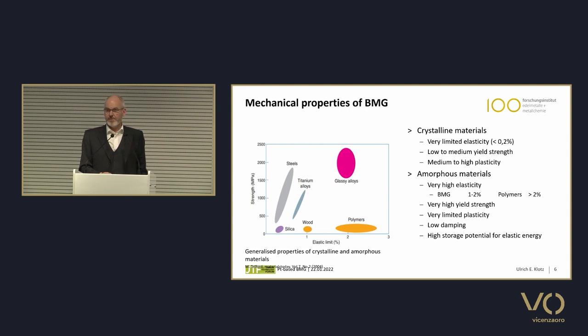Now, some properties of bulk metallic glasses, why are they interesting, or what is special with their properties, is shown in this plot. This shows the strength as a function of the elasticity. And we see several groups of materials, steels, titanium alloys, so classical conventional metals. They have high strength and a very low elastic limit. Usually we define 0.2% as the elastic limit in most materials.